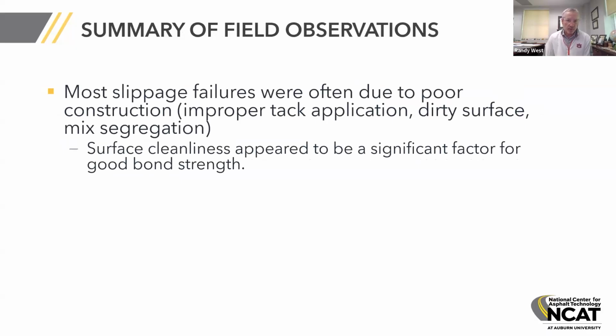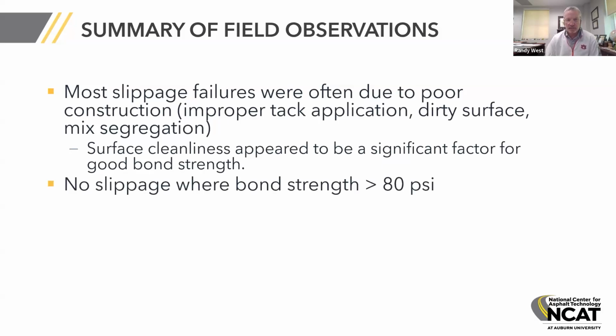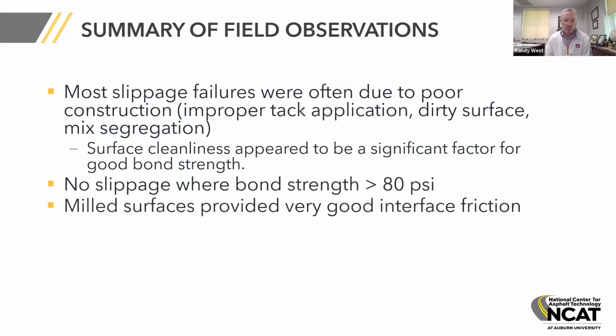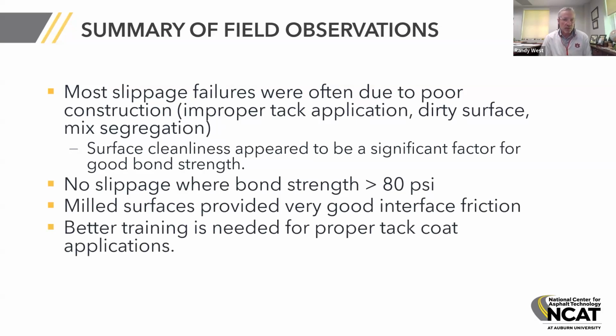Some of the observations from the forensic part were that most of the slippage failures were often due to construction issues, like improper tack application, dirty surfaces, mix segregation. And I think surface cleanliness is really an important thing that Nathan's already mentioned, and I know Sean will talk about that a little bit later. We did see that no slippage occurred where the bond strengths were at least 80 psi, and so that sort of helps support 100 psi as the criteria from the preliminary work. We also saw that milled surfaces generally provide good interface friction, as Nathan mentioned. And what is apparent is that better training is needed for inspectors and for paving crews on what a proper tack application looks like.